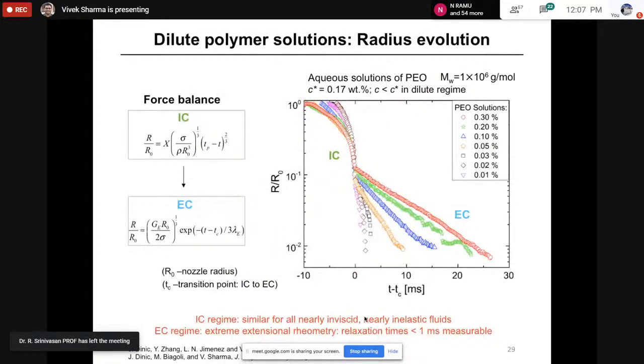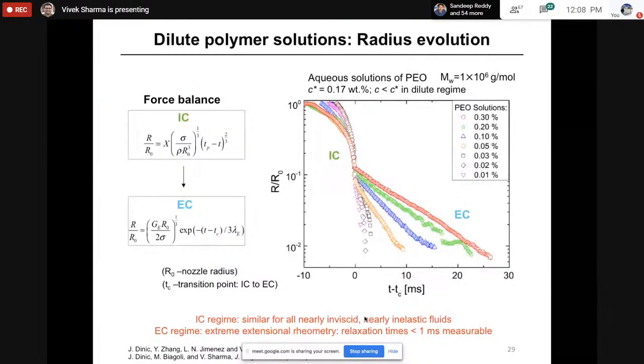Right. So one of the first things we did was to make measurements for a polymer solution. That's a dilute polymer solution. What that means is the number density of polymer coils is low enough that each polymer coil is far away from other polymer coils. There's a concentration called the overlap concentration, referred to here as c star. That's the concentration at which the number of coils is just enough that they start to touch each other, or they start to overlap. At overlap concentration, the polymer solution viscosity is 2 times the solvent viscosity. So all the polymer solutions that are shown here, except for 0.3%, have viscosity that's within 2 times water viscosity. For these polymer solutions, if we try to make measurements on CaBER, we get nothing. By the time the liquid bridge is stretched, all the action is over, and you're not able to make measurements of radius evolution. So commercial devices could not give us any measurement of extensional rheology or pinching dynamics.